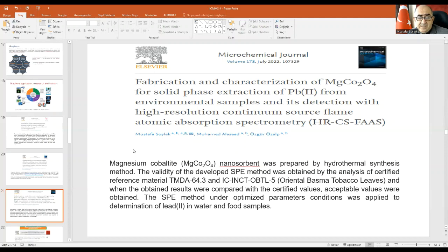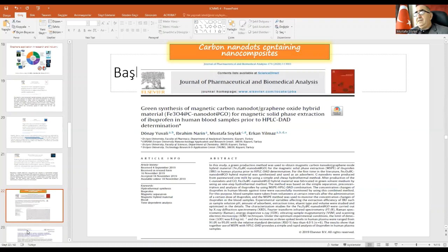Also, we have new materials, including carbon nanotubes and nanodots. You know that nanodots, quantum dots, are very attractive materials. We synthesized a magnetic carbon nanodots and graphene oxide hybrid by using hydrothermal synthesis, and we used these materials for the solid phase extraction of ibuprofen in human blood prior to high performance liquid chromatographic detection of these trace analytes.